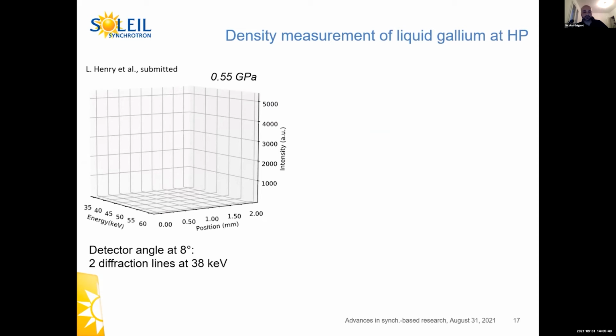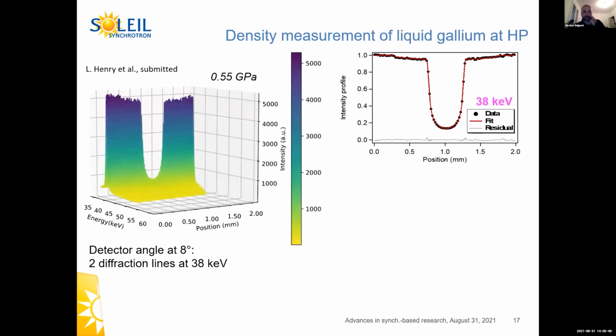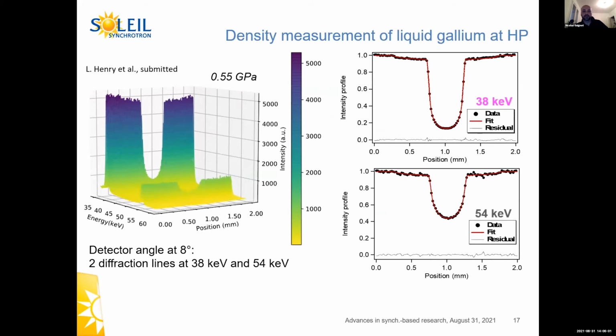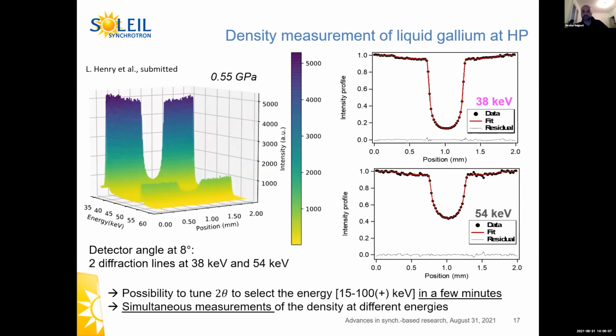If we put the detector angle at 8 degrees, we have two diffraction lines, very strong lines that we can record. The first one at 38 keV, and you have on the left the evolution of the intensity of that diffraction peak and the corresponding absorption profile on the right, and another line at 54 keV and the corresponding absorption profile. And you can see that we have two interesting benefits here.